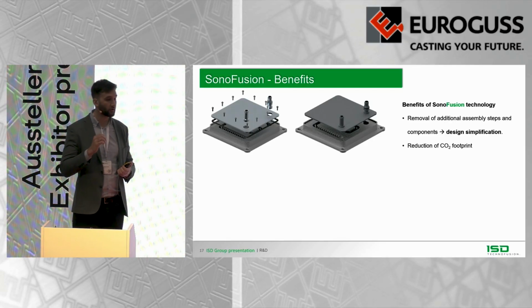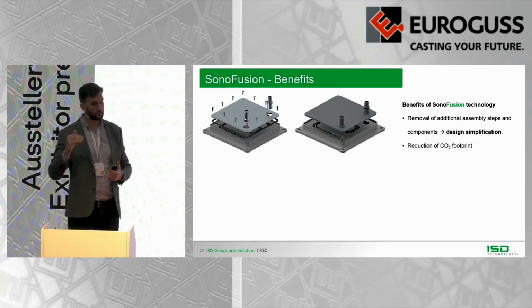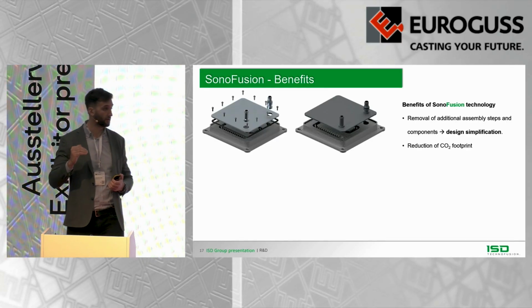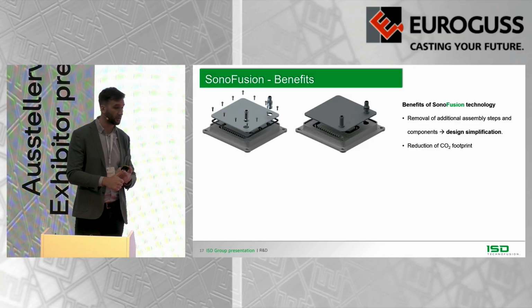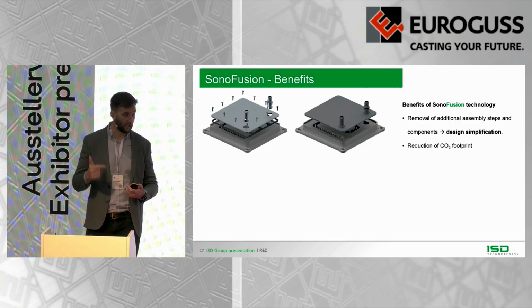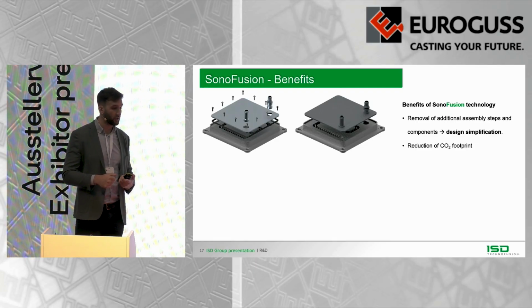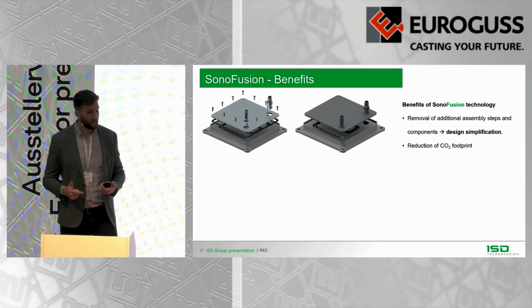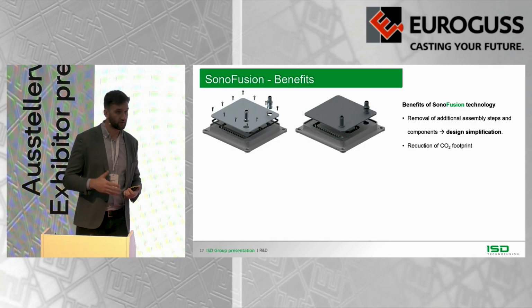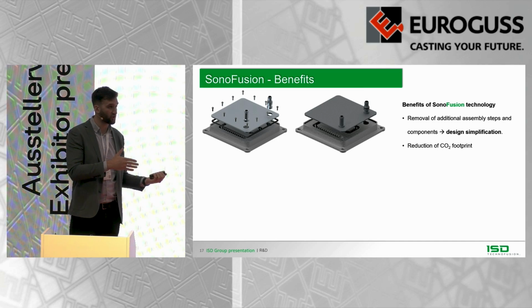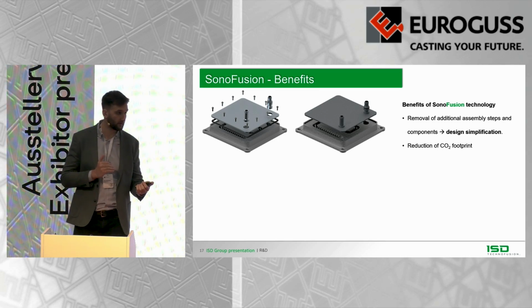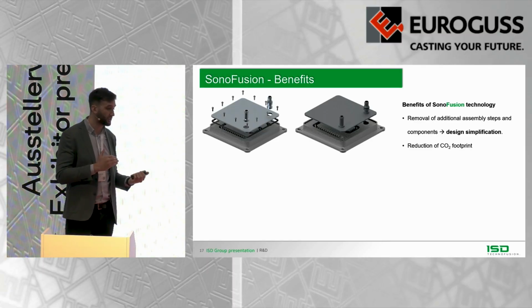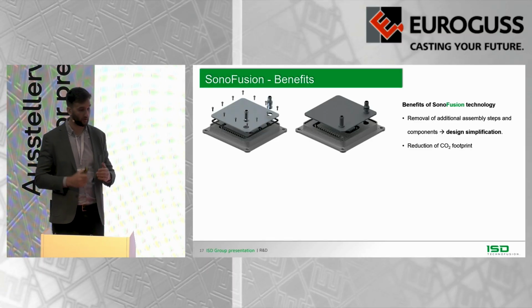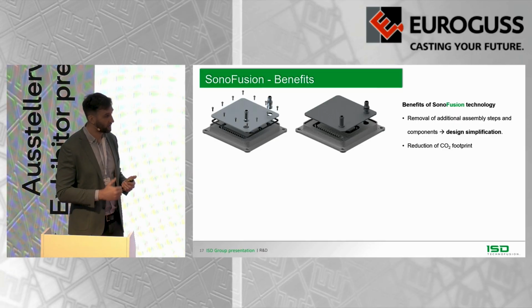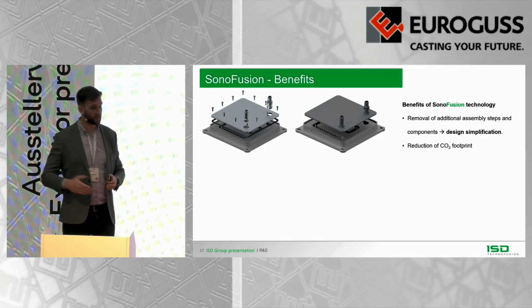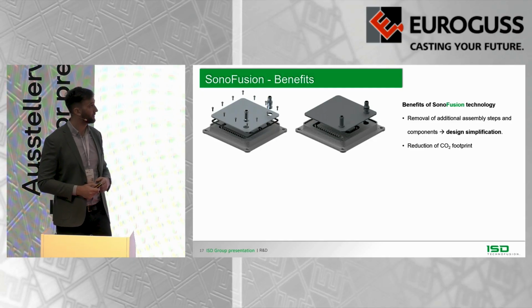But the part cost of the polymer cover in the end will be 50% or even more cheaper than the casting. Why? Because you only need an injection molding tool, which has 10 times the lifetime of a casting tool. You don't need any additional trimming tools or any additional machining. And also the energy consumption of injection molding is much, much lower because you normally injection mold polymers at around 280 or 300 degrees Celsius, while you cast at 600, 650 or whatever degrees. So the energy consumption is much lower, and obviously also the process flow is shorter, which eventually results in much lower cost of the part itself.